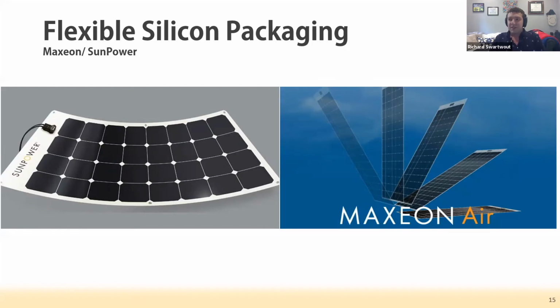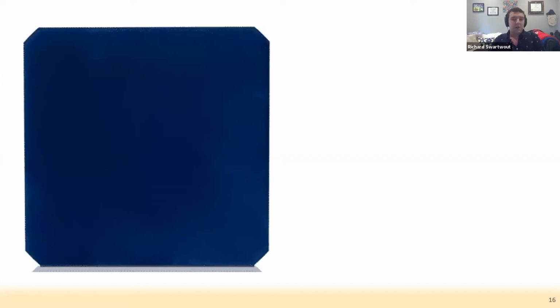The thing is that there's fundamental limitations to using silicon. If we take one of these SunPower cells, this is just a normal photo image, you can't see much with this method. But if you look at these cells under a photoluminescence inspection system, you'll see something like this. They're not always perfect, like this one.